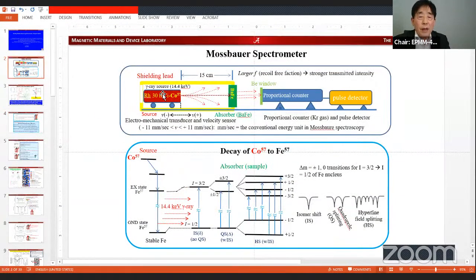Why do we say velocity? Because this gamma ray source will be moving forward and backward between minus v velocity and positive v velocity. In this case, we control the velocity of this isotope, the cobalt isotope carrying car, between minus 11 millimeters per second and plus 11 millimeters per second. Why are we talking about millimeters per second? In Mossbauer spectroscopy, we use millimeters per second as the velocity, as the conventional energy unit. So we can think of V, the velocity of this isotope carrying car, as meaning the energy.